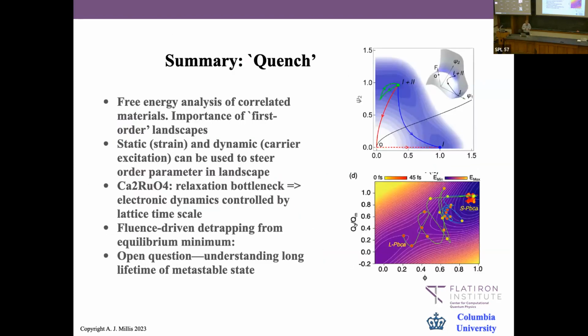So this is basically what I told you before. And I think we see clearly that free energy analysis is a useful way to look at the physics of these materials - that many of the interesting transitions have first order landscapes with electronic and lattice degrees of freedom mixed, that static, that is to say strain, and dynamic carrier excitation can be used to steer the order parameter in the landscape.